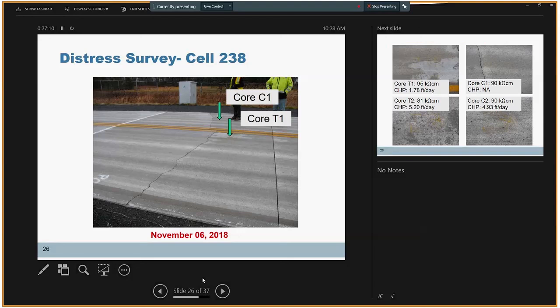So a few weeks ago, we went to the MnROAD facility, and with support from MnROAD technical staff, we took cores to investigate the reason for these cracks. It turns out that the main transverse crack we had here was due to some utility line underneath the pavement.